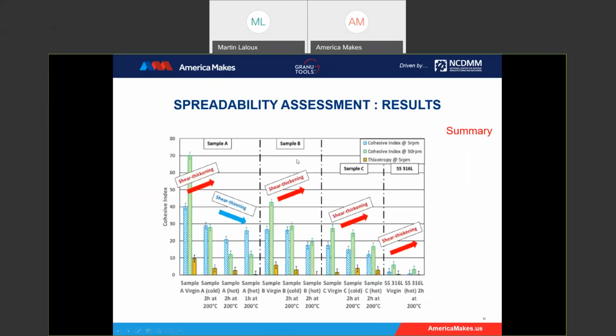So the summary: we observe here the cohesive index for the powders. When we take a look at the virgin samples, sample A has the highest cohesive index compared to the other powders. Also, the cohesive index increases with the rotating speed. This trend is the same for the 4 virgin powder samples, but more dominant for the finest powders due to the higher possibility of van der Waals forces, which is obvious. So finest powders have more chance to form agglomerates.